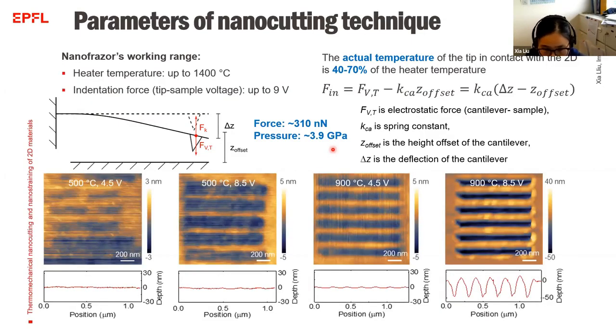Experimentally, we also did some measurements to compare the parameters. First, have a look at the left two images here. We applied a low temperature, 500 degrees C, and either a low voltage or high voltage, and we cannot cut 2D materials. It means the PPA does not evaporate, and the sublimation of PPA is essential for this cut. If you cannot make the PPA evaporate, you cannot cut the 2D materials. You only slightly strain 2D materials.